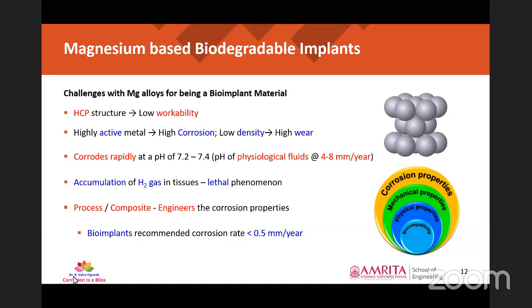Coming towards the corrosion perspective, magnesium alloys corrode rapidly at a pH of around 7.2 to 7.4, which is the pH of physiological fluids, at the rate of 4 to 8 mm per year. But the recommended corrosion rate for biodegradable implants is around 0.5 mm per year. If this happens at a corrosion rate of 4 to 8 mm per year, that will result in accumulation of hydrogen gases in the tissues, which is a lethal phenomenon.